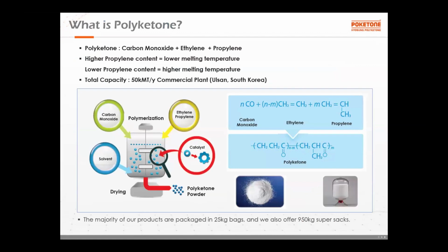The polyketone polymerization process: the monomers are carbon monoxide, ethylene, and propylene. Those monomers come here, and we use palladium as catalyst and methanol as solvent, with time and pressure together, and then we make the polyketone powder. Actually, that is wet powder. That's why we go through the drying section and then to the pelletizing extruder section.